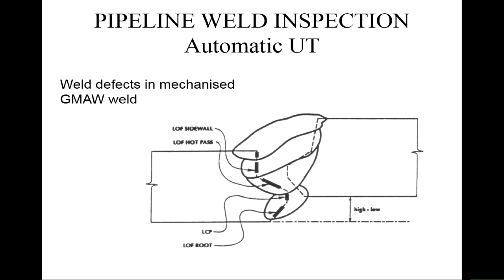You can see these height mismatches, you can see different amounts of weld metal are deposited, so the offsets of the weld metals, all of which can have an effect on the overall response. So instead of collecting the data from one position in the weld, you might want to collect the data at this height, at this height, at this height. And if you know what the welding procedure is and how many weld passes and how thick each pass is supposed to be, you might be able to set up an automatic system that interrogates each of those passes. And that's why we go for automated systems, because it gives you much more information about all parts of the weld.